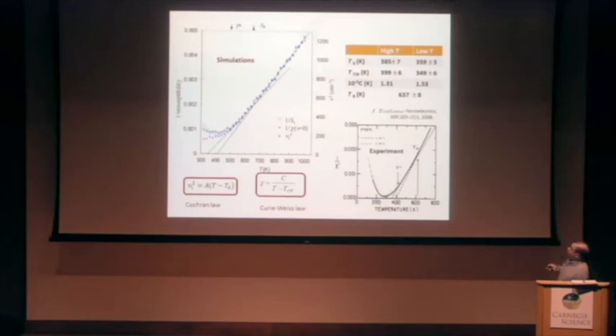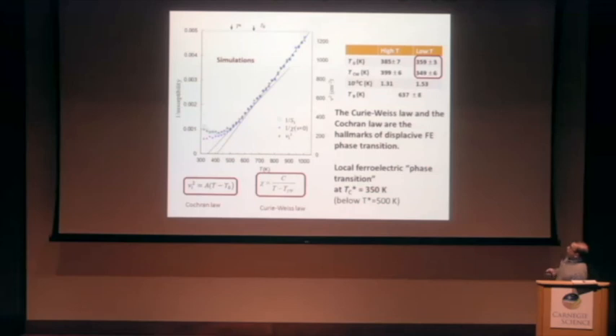The second Curie-Weiss law has been reported experimentally with the same parameters in this paper. The second Cochran law couldn't be observed because the frequency and temperature range is unavailable for experiment. But the Curie-Weiss law and Cochran law are the hallmarks of a displacive ferroelectric phase transition. We can say that this looks like a displacive local ferroelectric phase transition at temperature T-star, 350, and that is why we introduce this temperature as a new characteristic temperature in PMN and designate it as TC star to distinguish it from T-star and the Curie temperature observed in the PMN crystal at 210 K.